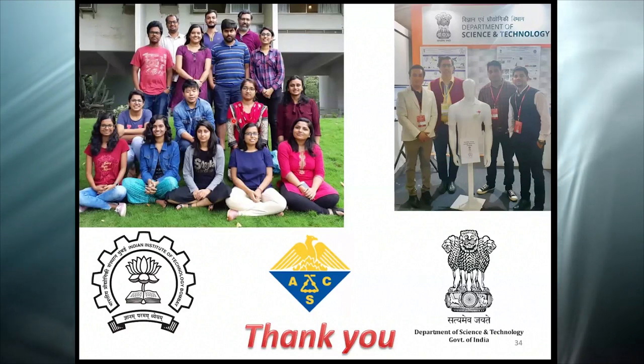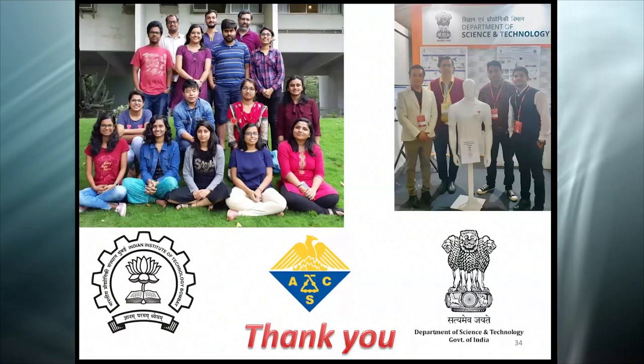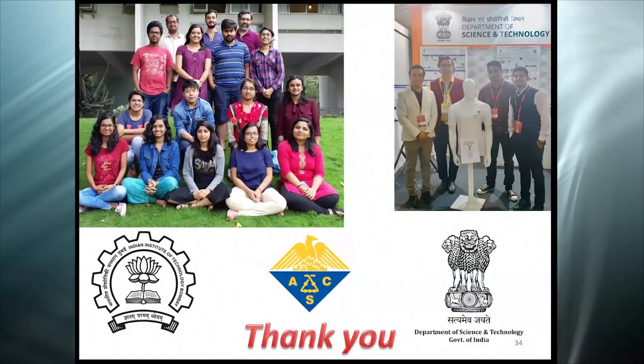Okay, Manas Ranjan asked, how can it be washable? Because the way we have put it, we have encapsulated it with PET sheets. We have done this lamination process, and that basically protects it from any external environmental conditions. So even if you put it in a washing machine, soak it in water, add detergents, nothing is going to penetrate this PET packaging. So the packaging is what makes it washable, wearable and mechanically resilient.